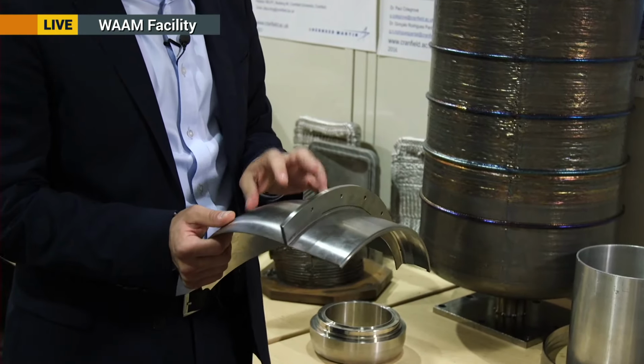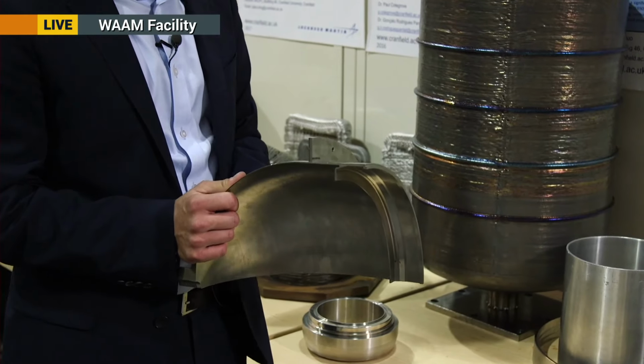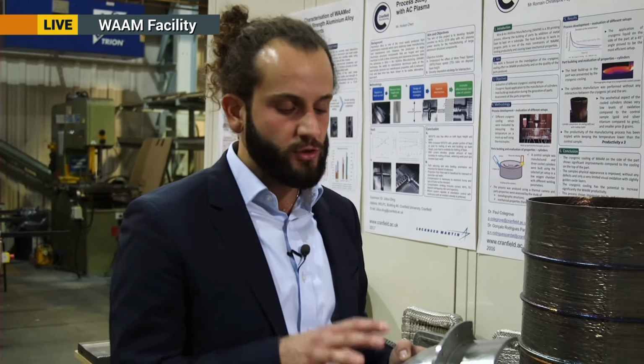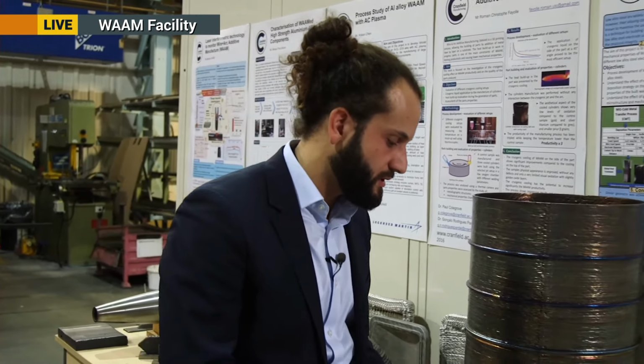Another attractive point for this component was that because you are no longer constrained by the set of forging tooling that you need to have if you go down the traditional route, now you can change the shape and the size of your tank to match the requirements of the mission. So again, you can minimize the amount of fuel that you take to space. And again, each kilogram that flies to space costs about 10,000 pounds. So if you can reduce some weight, you're also reducing your expenditure.